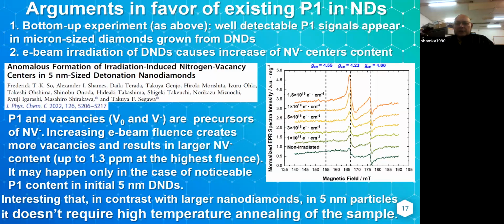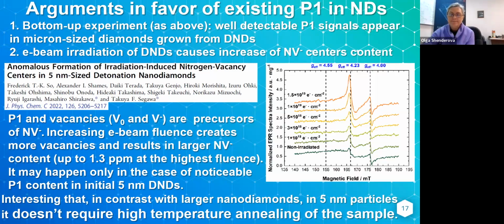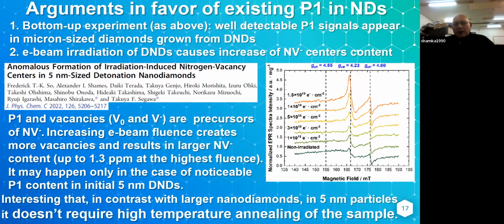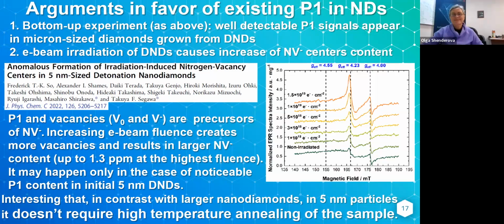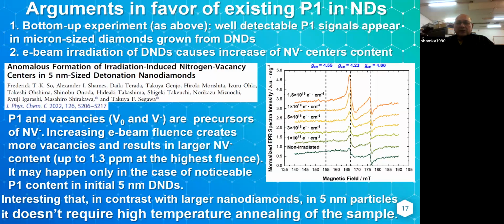Magnetic particles attached to the surface of nanodiamonds, even of small or larger sizes, very strongly affect the hyperfine structure by broadening. But what's interesting is that when you have quite clean diamond and reduced size with no new magnetic impurities there except dangling bonds, the P1 line doesn't change, it just goes down with no broadening. Broadening is a very well known mechanism, and it also works even for larger particles. And I think that this magnetic noise will affect brightness and all parameters of NV minus centers. I think that the magnetic modulation method is based on this effect. You also change the relaxation time.